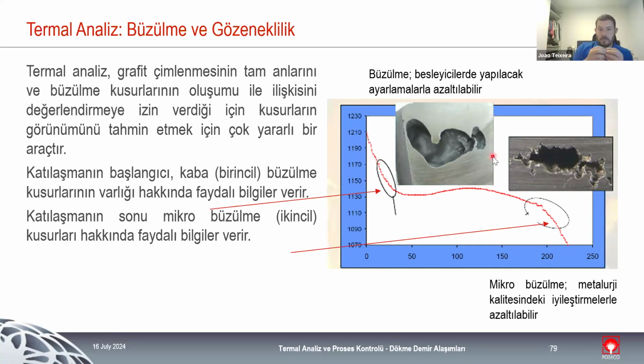When we have micro shrinkage, so shrinkage that is really small, sometimes it's not easy to identify micro shrinkage versus porosity. An easy way to identify is that normally porosity is really perfect. The porosity defects, the holes, are nearly perfect because it was gas that was trapped inside the melt, and the gas exploded at some point, but it's easier for a gas to stay as a perfect round than to stay in a different shape. It's less energy for that state. So when the gas bubble explodes, that part was not filled with metal. So it stays a perfect round or almost perfect round shape. And micro shrinkage is everything but perfect. So one of the easiest ways to identify it is the shape of the defect.